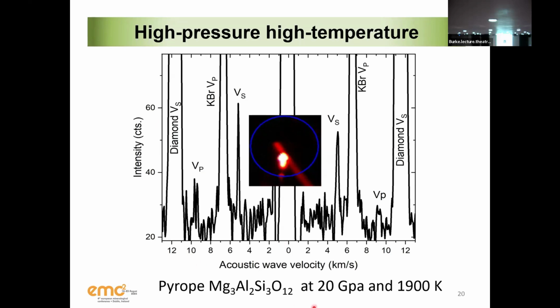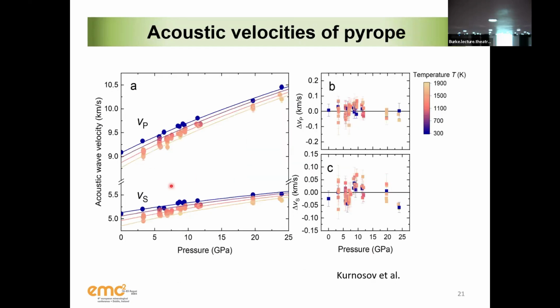So this is my pyrope at 1900 K, plus or minus 60, 70, maybe also 100, depending on how well we can control that emission. And these are the acoustic velocities measured at 20 GPa and that temperature: VS and VP, the shear wave and the longitudinal wave. Of course, the Brillouin spectrum is dominated by your diamond, as usual, and in this case also by your sample, your salt. So we have to collect for quite a long time to be able to see these velocities. But then you can see we could do quite a lot, because we can increase pressure and temperature on the same crystal.